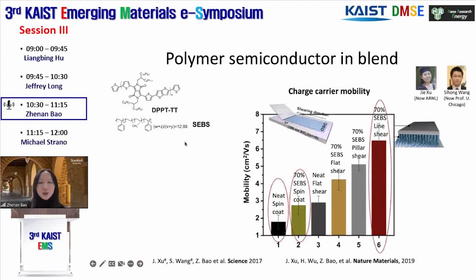On the other hand, we were also interested in looking for a more general approach. In polymer science, a common approach to achieve two functions is to have a blend. In this case, we need semiconducting property and the stretchability. So it's natural to think about having a blend that has semiconductor and a stretchable polymer. But the problem with the electronic polymer design is that this kind of design for electronic conduction will significantly degrade the conduction because the insulating material will take a fraction of the conductive components. And furthermore, the insulating material can get in between the conductive components and further reduce the charge transport.